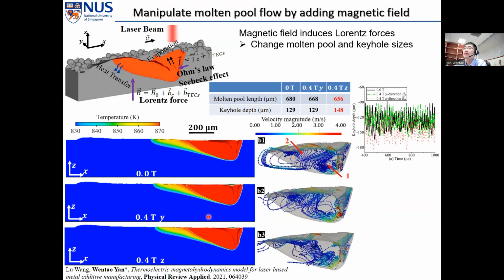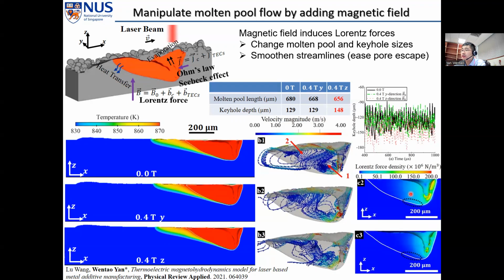But when we add an external magnetic field, we can eliminate the vortex in the rear part of the molten pool. So when a keyhole pore is formed here, it can escape due to this flow pattern in the rear part of the molten pool. Also, the Lorentz force near the molten pool boundary is strong enough to meet the criteria that experimentalists found in experiments, which can potentially refine the grains.